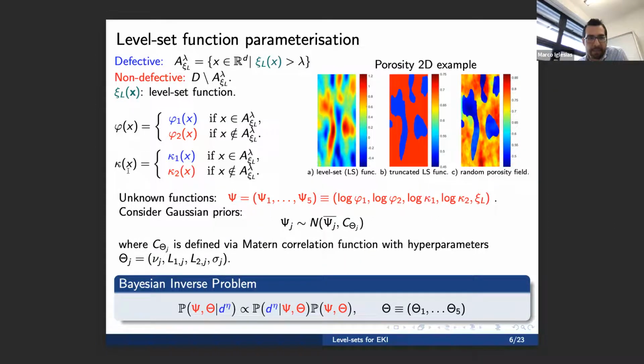And then we can do the same for permeability. So we have made the problem more complicated, going from estimating 2 functions to estimating 5 functions. I'm going to consider the log of all these functions to make sure they are positive when we do the inversion. So we have 5 functions to infer: log phi1, log phi2, log kappa 1, log kappa 2, and the level set function that will give me the interface between defective and non-defective.